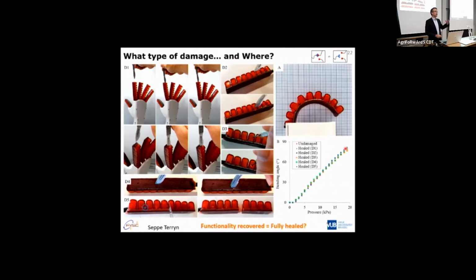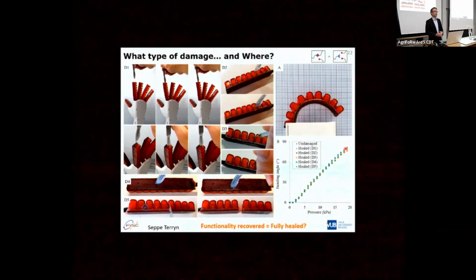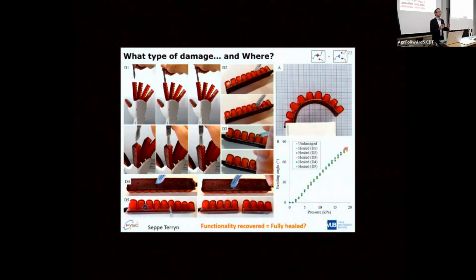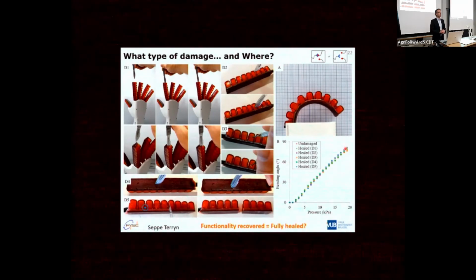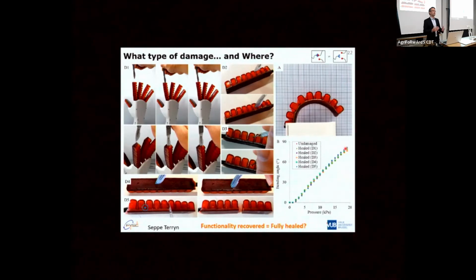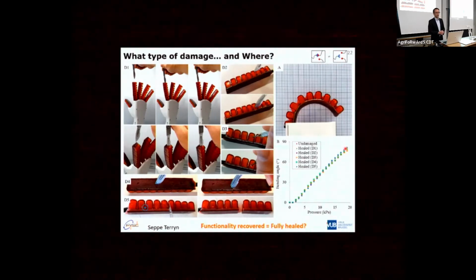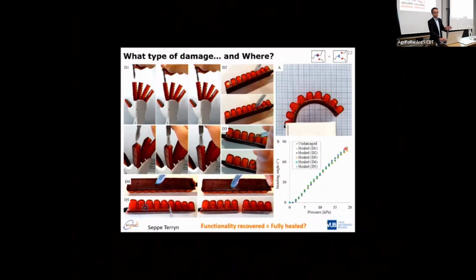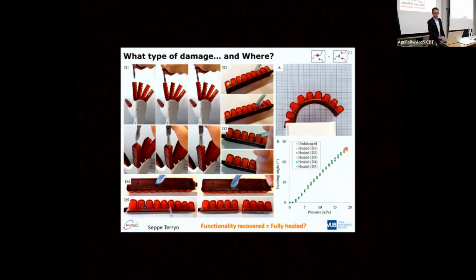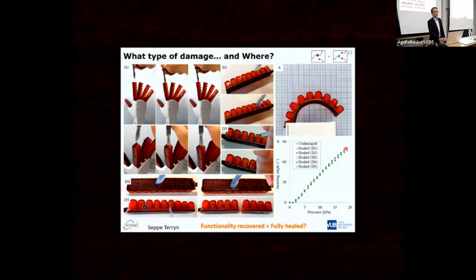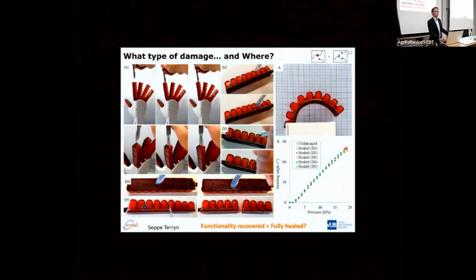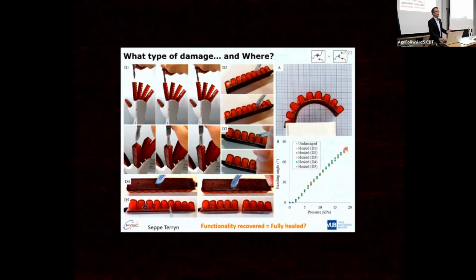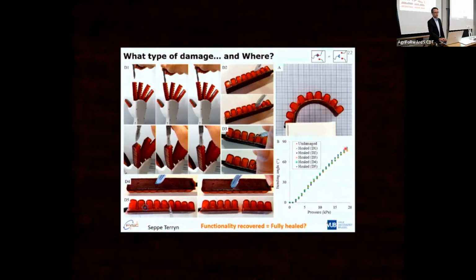Maybe if you try to increase the pressure up to closer to its limit that you determined in other experiments, maybe you'll find out that it's not yet fully healed and that there are still scars that are in a kind of intermediate state. They are closed, so you can pressurize the system, but it bursts at a much lower pressure than the maximum design pressure that you aimed for. So there is a difference between the two, and it will depend on what you're aiming for, maybe what is most relevant for you. We might be designing healing cycles with which you fully recover the properties that you target for, but with a much shorter healing cycle, you might be able to fully recover the functionality.